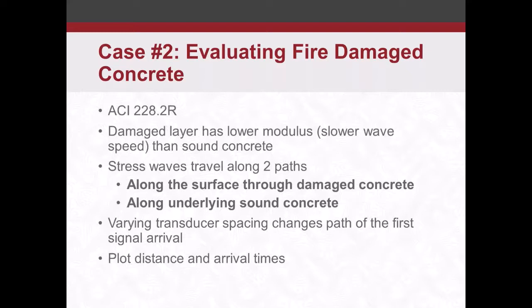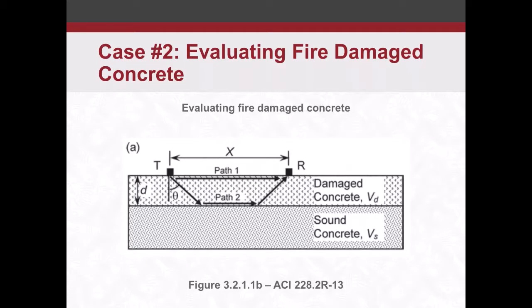And what we do is we vary our transducer spacing, and we take various readings. I don't know if I spaced it at 2 centimeters or 5 centimeters apart, but we do tests at different spacings, and then you plot the wave speed versus distance or arrival times. This is also in ACI 228.2. So here's our transducer. We're testing on the same surface on this one. The other project we were testing on opposing surfaces.